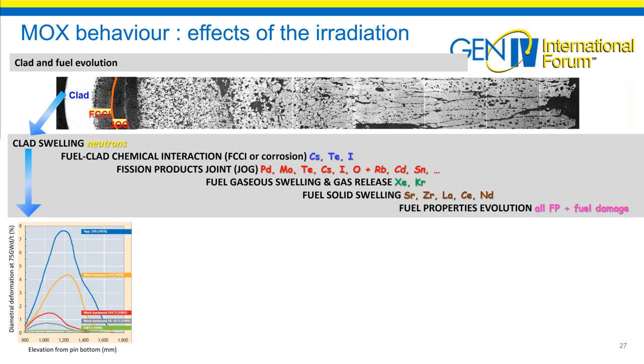So this slide is to illustrate that due to the neutron effect in combination with the temperature, the clad is swelling. We have an evolution of the mechanical properties of the clad that can be affected. I have no time to describe exactly all the phenomena in the cladding, but this is only one figure to illustrate, in particular, the diametral strain due to the swelling induced by the neutron. It's a strain as a function of the actual positions of the pin. Our preference is clearly to have a stainless steel that has demonstrated a low level of swelling, like the austenitic 15-15. So next slide.